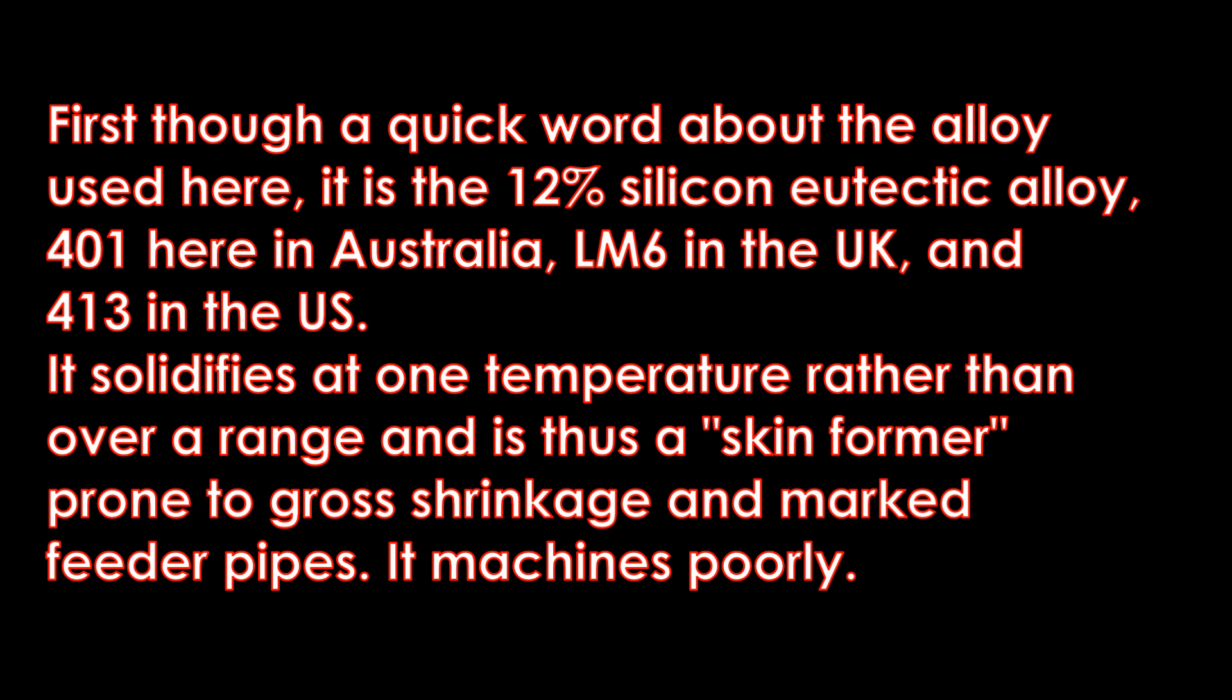First though a quick word about the alloy used here. It is the 12% silicon eutectic alloy, 401 here in Australia, LM6 in the UK and 413 in the US. It solidifies at one temperature rather than over range and is thus a skin former, prone to gross shrinkage cavities and marked feeder pipes. It machines poorly.